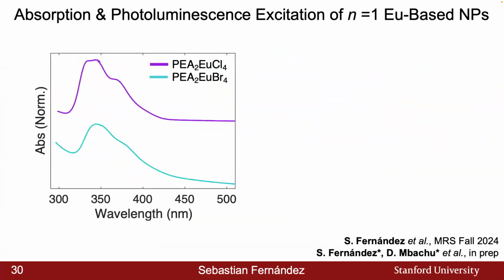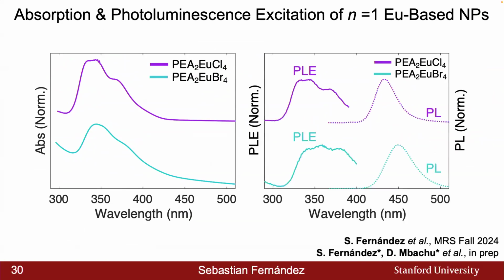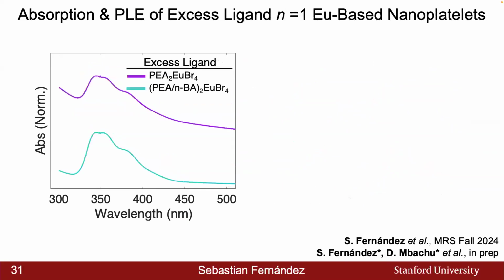So again, these are the N=1 under-reacted 2-to-1 ratio that in theory should be these materials. And we can see that we have a very similar case here where we have the strong absorption peak at around 350 nanometers, and that we have really good adherence between the photoluminescence excitation and the absorption itself with the photoluminescence that has already been shown. And for these materials in the solution state, we have PLQYs of around 0.5% and 2.25% for the chloride and bromide respectively.